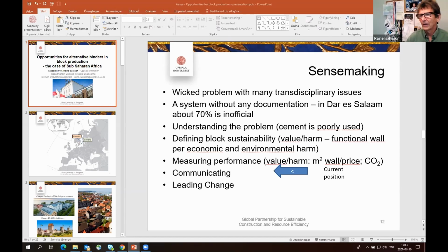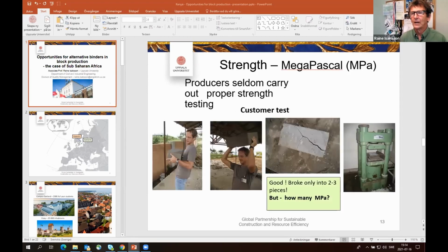And a sustainable block, the value could be defined as I exemplify here, measuring the functional value: a square meter of wall which is good enough compared to the price and compared to the CO2. When we hear about the soil cement blocks, fine, but 7% cement is too much, because with 7% cement I can already make a very good concrete block, but the carbon footprint is still too high there. So here in the soil cement also, as we heard, if we can somehow substitute the Portland cement, we could then get both the price and the carbon footprint down. So after some 10 years of work, this is as far as I come. Not so good for a project where I maybe spent 2,000 hours, going to Tanzania maybe 20 times.